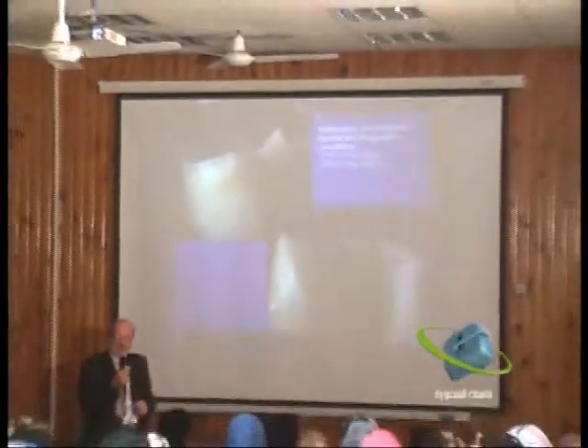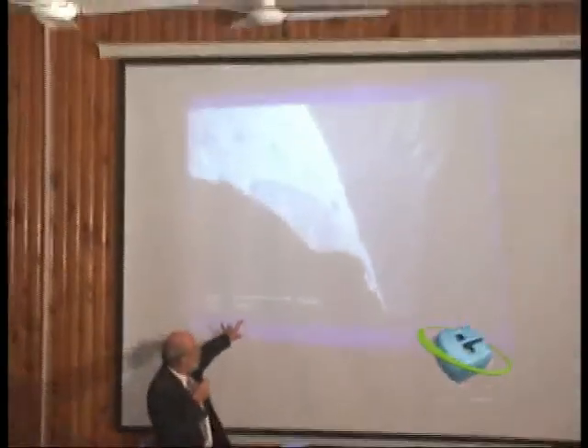Now, when you're going to make these materials, one of the issues, often in conservative processes, is that you would like very tapered margins at that edge to be able to minimize the amount of tooth structure removed. But the problem is that often then leads to a very sharp ridge-like structure, and that sharp ridge makes it very easy for cracks to initiate from this area. You notice this is 200 microns, so you have a very, very sharp edge. Even though you have a strong material here, when you have such a thin section like this, it is very easy to nucleate a crack here. Once the crack is nucleated, then it will easily grow in that system over time.